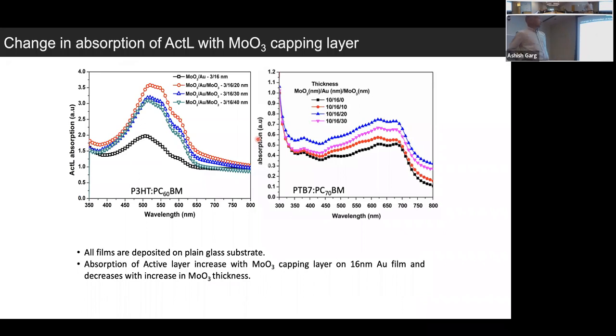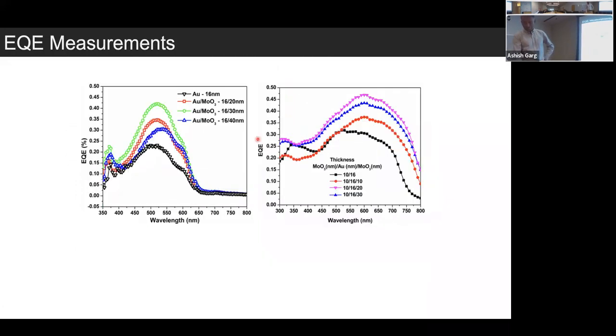You can also look at the problems in the EQE, external quantum efficiency, data. Of course, at those thicknesses, the light absorption is much higher. So, this is the absorption of light in the active layer. Absorption of light is very high as compared to other thicknesses, and that is because of transmission of more light from the top electrode.